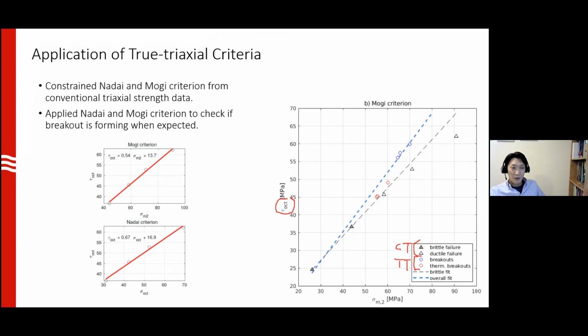Namely, the conventional experiments show a weaker prediction compared to what we observe in the borehole. So this tells us that even though we can constrain a criterion from cylindrical samples, that cannot be applied to the borehole geometry.